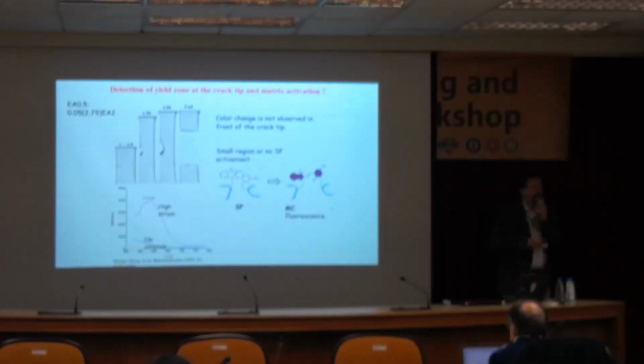So then, of course, we were wondering, particularly my student, whether you would actually see something in this case. And it turns out that you do. So here, this is a low strain. The crack tip is hard to see, it's yellow here, but critical strain means just before the crack propagates. And here you can see the yellow dot here, which means that there is a little bit of yielding in the material in front of the crack.